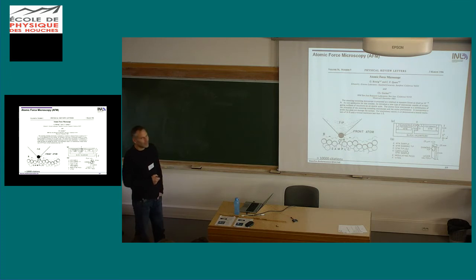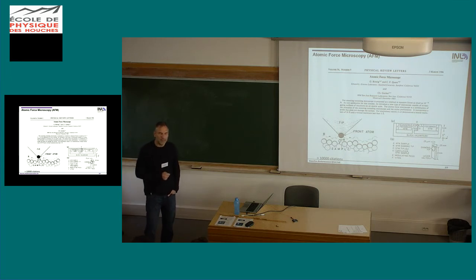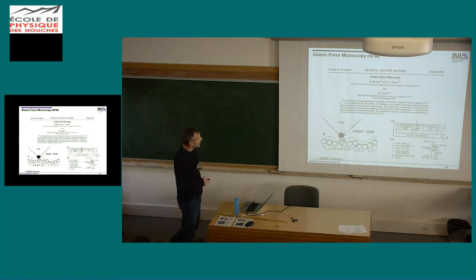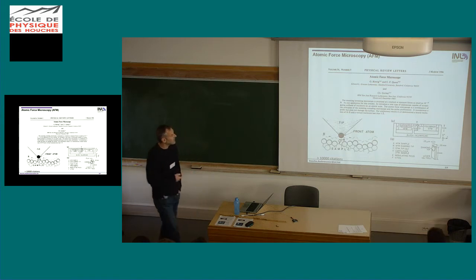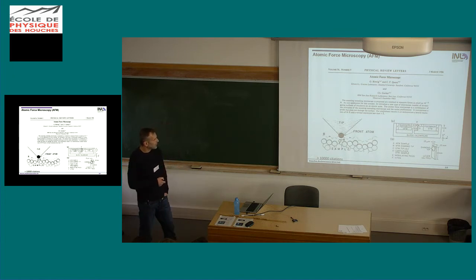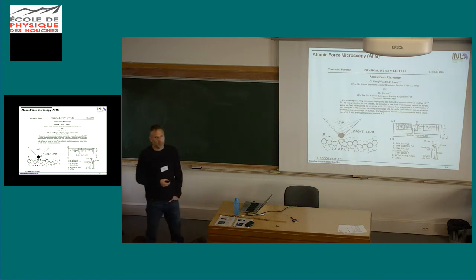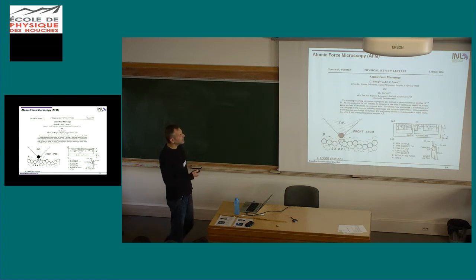Atomic force microscopy. One of the big disadvantages of STM is that you actually need a conductive sample because you're measuring a current. So if your sample is not conductive, you're stuck. You cannot use the scanning tunneling microscope. And therefore Gerd Binnig, Calvin Quate and Christoph Gerber developed the atomic force microscope. This is a paper from '86. It received more than 10,000 citations, so it's a very common technique. You have probably heard this many times already. Both of these microscopies enabled nanotechnology to some extent.